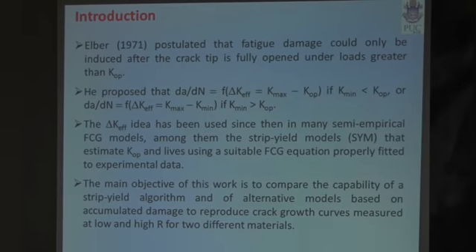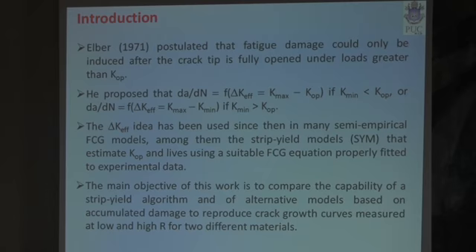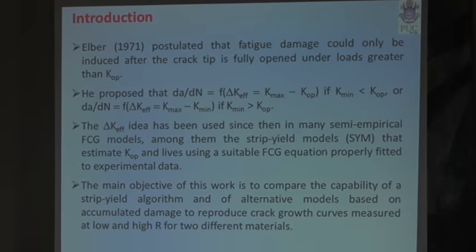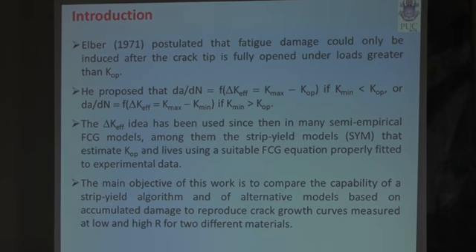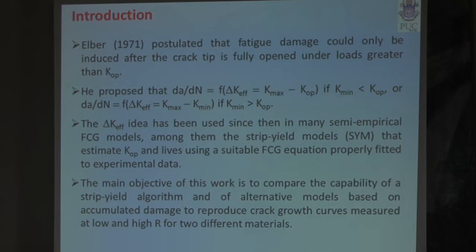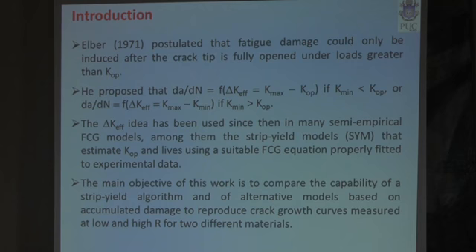After discovering crack closure, it was postulated that fatigue damage will only be induced at the crack tip if the crack is fully open during loads greater than the opening load. He proposed that the crack tip driving force would be the effective stress intensity factor range. This idea has since been used to develop many models, semi-empirical models, among them the strip yield models that estimate the crack growth rates and fatigue lives, using a crack growth rate equation fitted to experimental data.